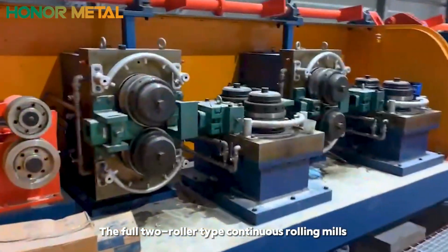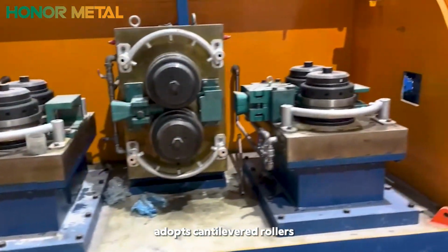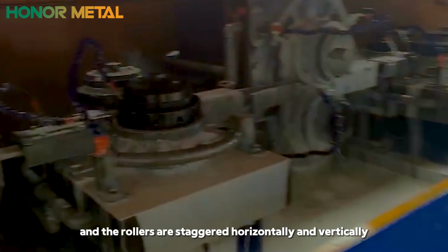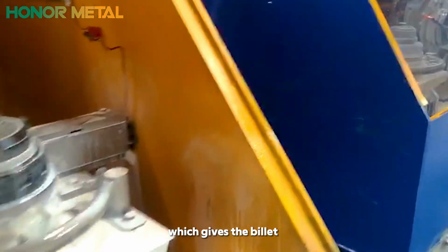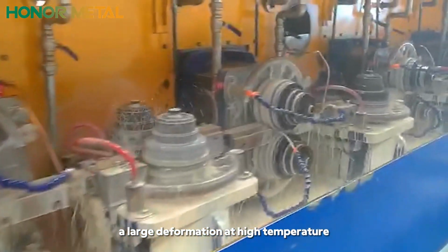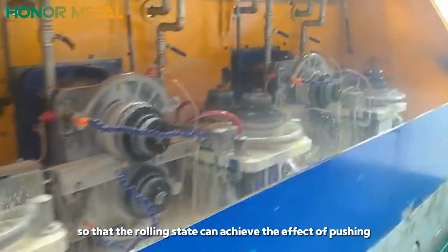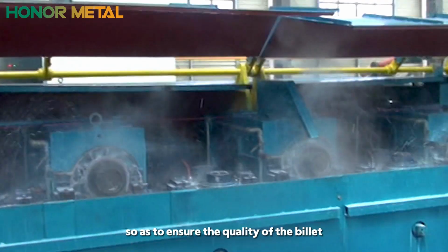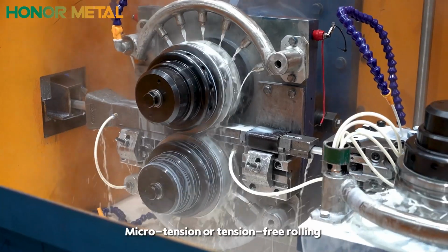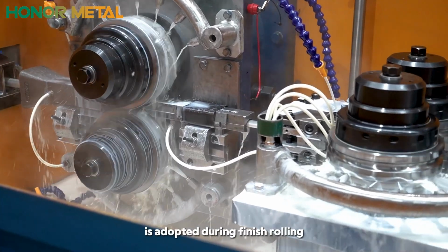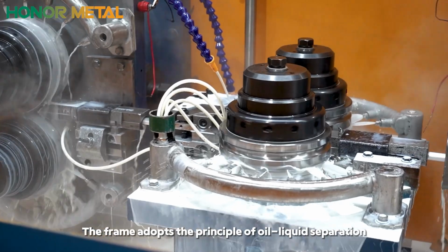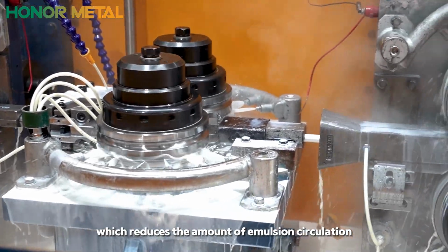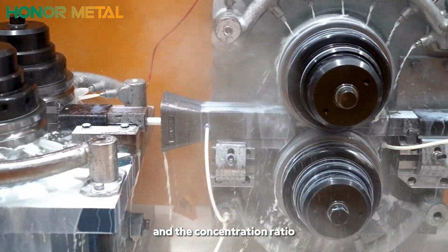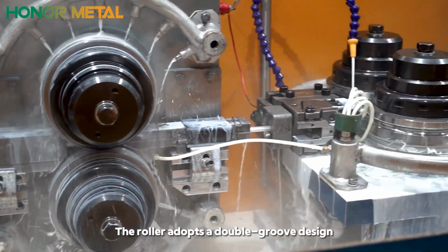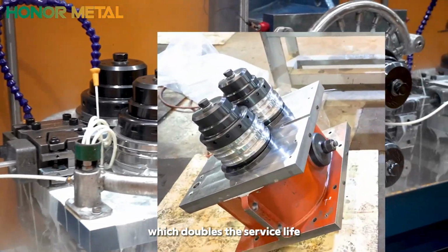The full 2-roller type continuous rolling mill adopts cantilevered rollers, and the rollers are staggered horizontally and vertically. A large compression ratio is adopted during rough rolling, which gives the billet a large deformation at high temperature, so that the rolling state can achieve the effect of pushing, squeezing, and pressing so as to ensure the quality of the billet. Microtension or tension-free rolling is adopted during finish rolling. The frame adopts the principle of oil-liquid separation, which reduces the amount of emulsion circulation and the concentration ratio. The roller adopts a double groove design, which doubles the service life.